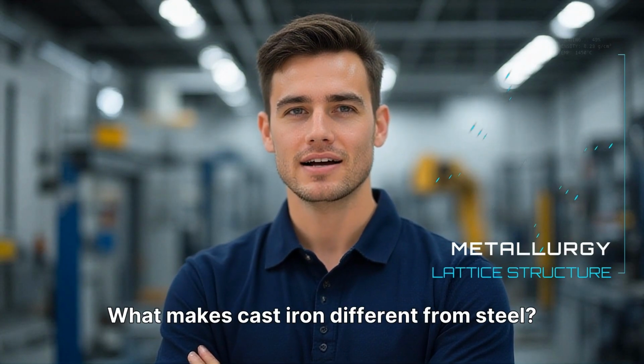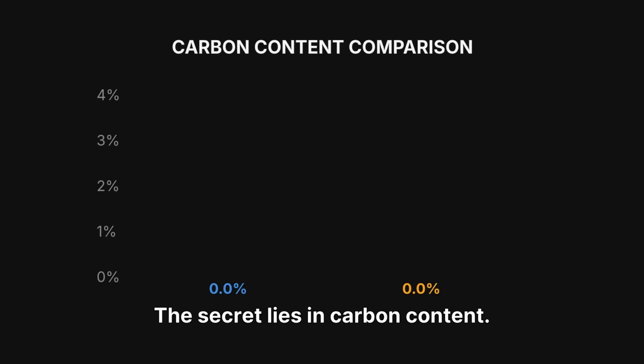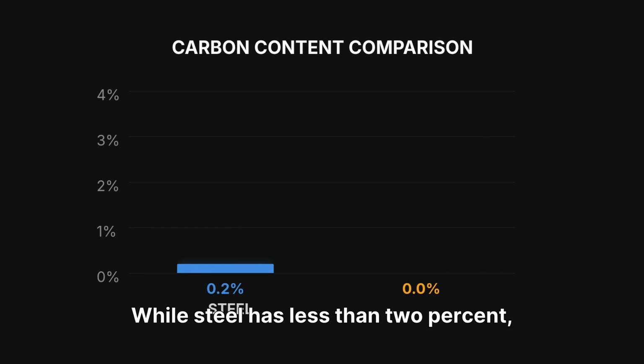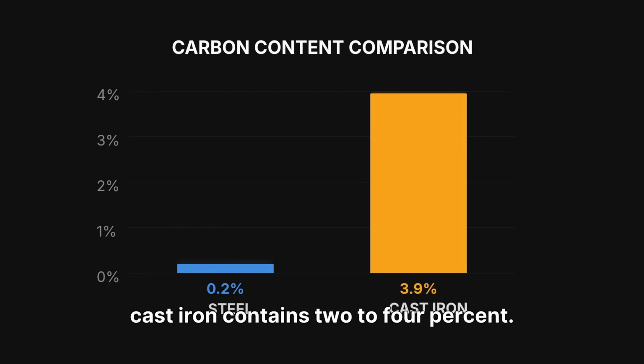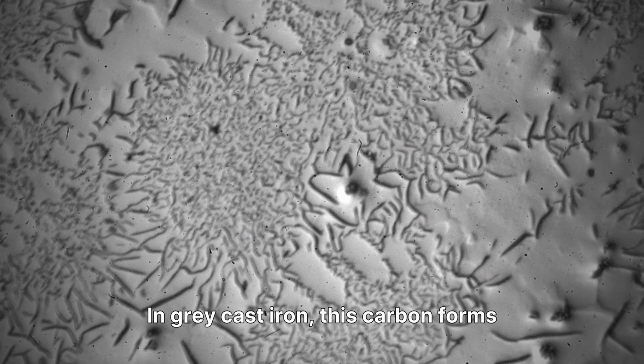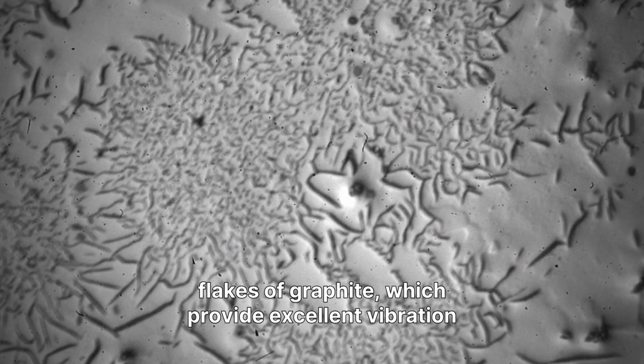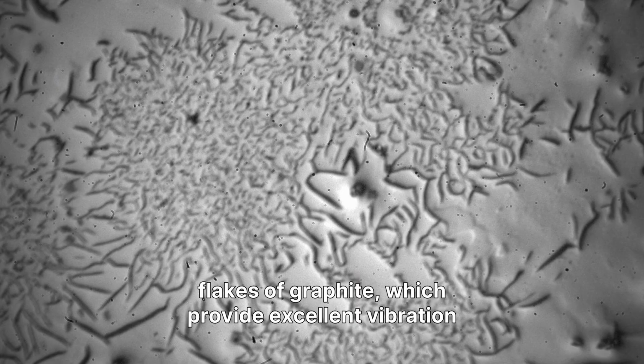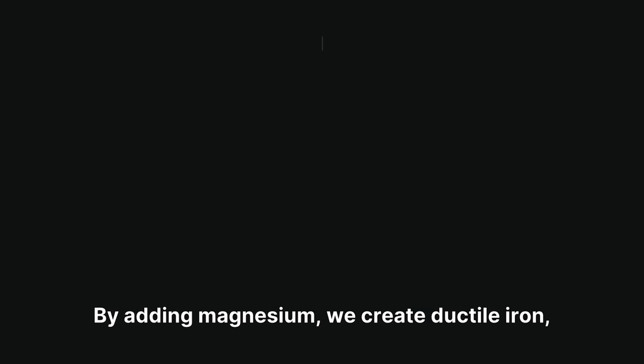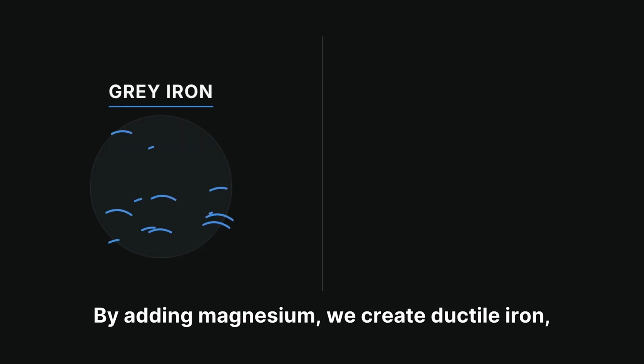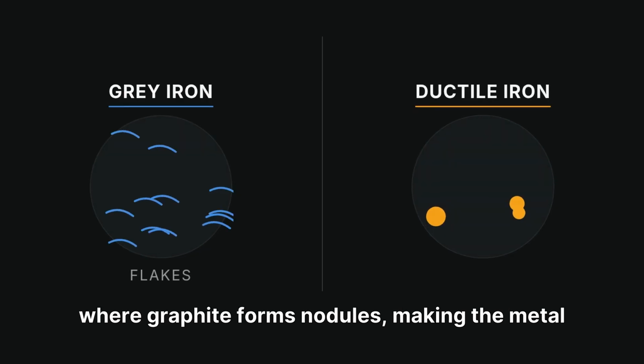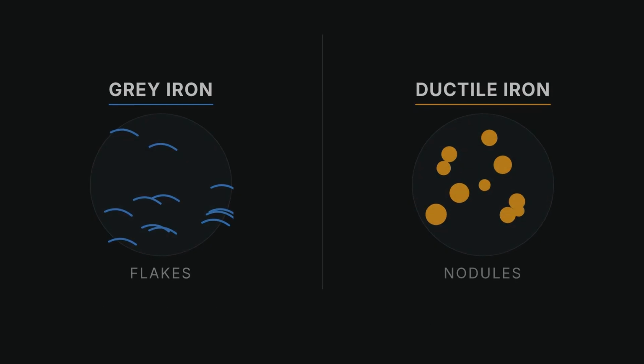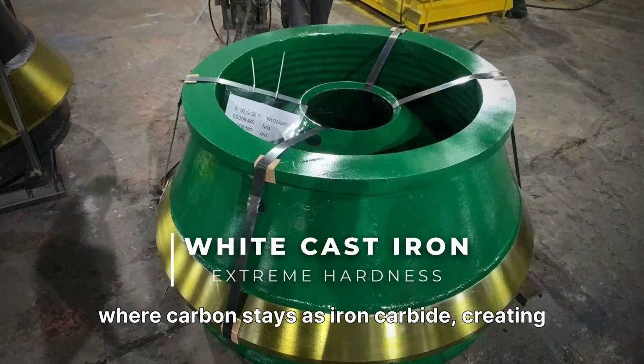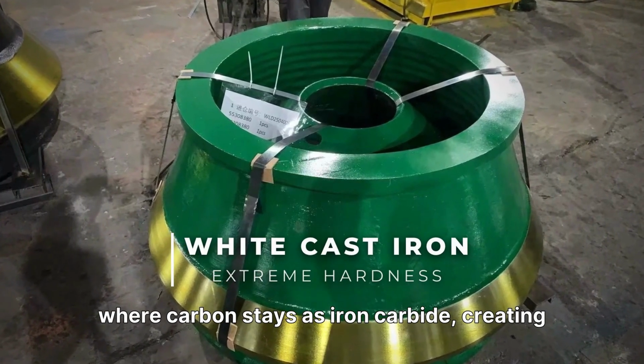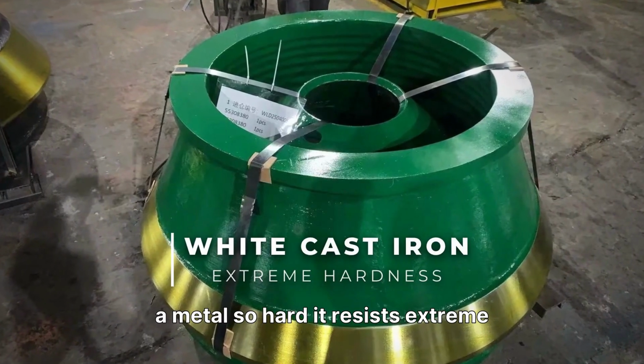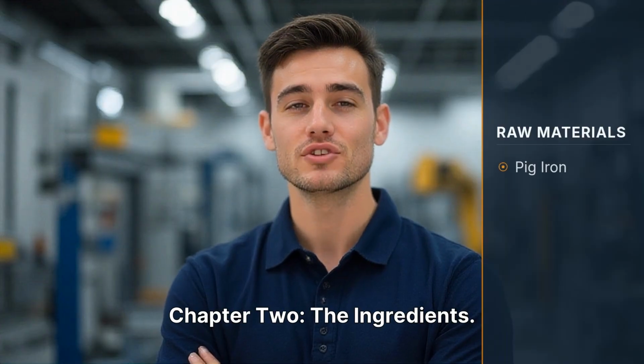What makes cast iron different from steel? The secret lies in carbon content. While steel has less than 2%, cast iron contains 2 to 4%. In gray cast iron, this carbon forms flakes of graphite, which provide excellent vibration damping and machinability. By adding magnesium, we create ductile iron, where graphite forms nodules, making the metal strong and flexible. And then there is white cast iron, where carbon stays as iron carbide, creating a metal so hard it resists extreme wear.